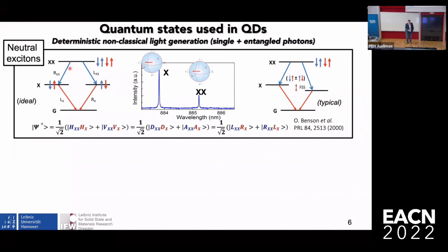Because the electron and hole spins shouldn't talk to each other, but they do have a weak interaction. The hole is a p-type Bloch orbital. The electron is made from s-like Bloch orbitals. So they shouldn't couple via contact interaction. They do actually have an exchange coupling, and that mixes these two states here. It results in two linearly polarized states with a slightly different frequency. And this is what we call the fine structure splitting.